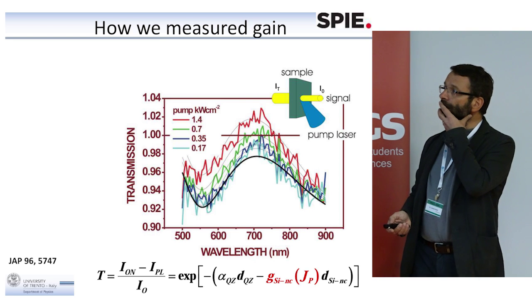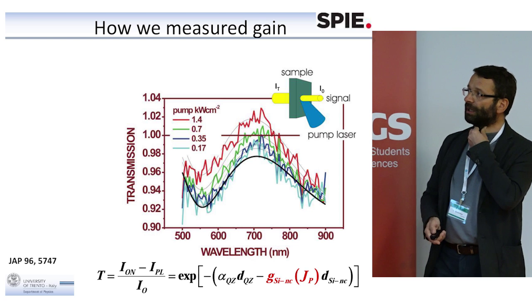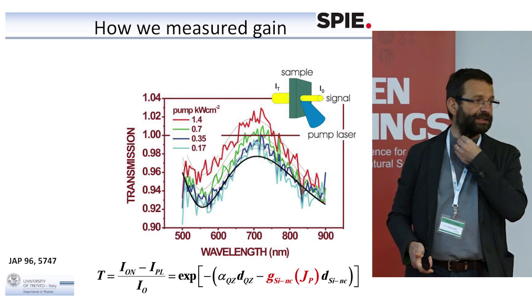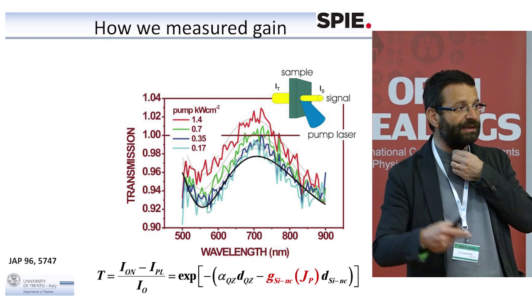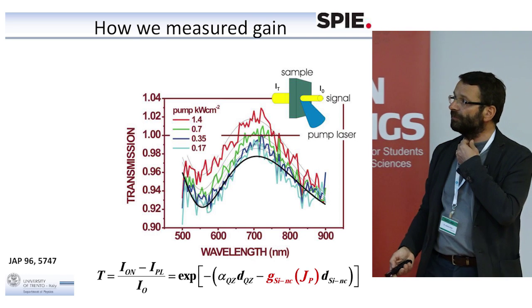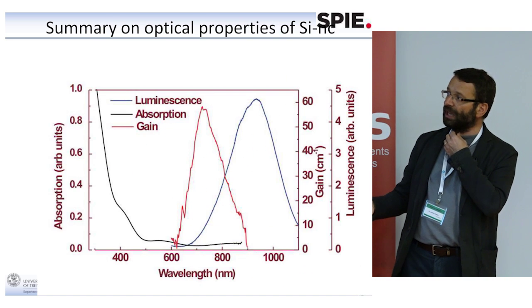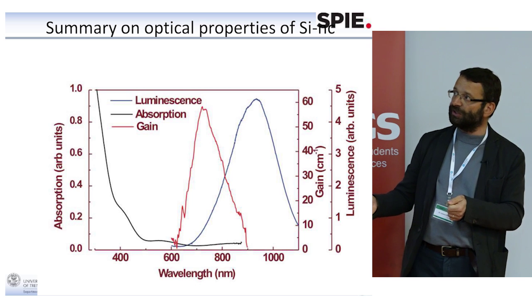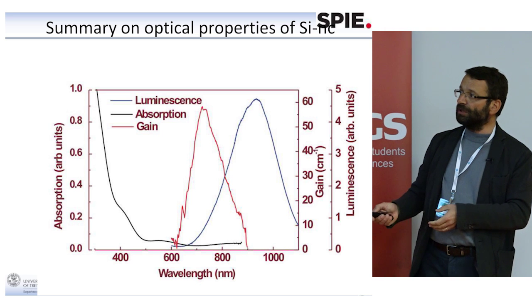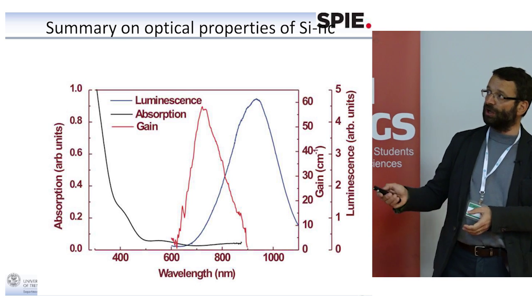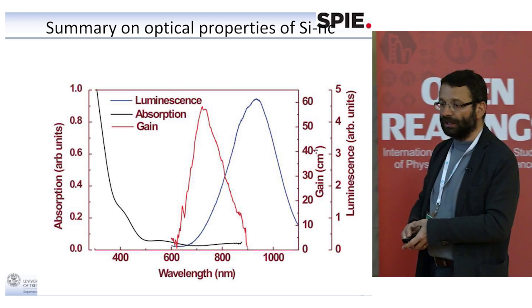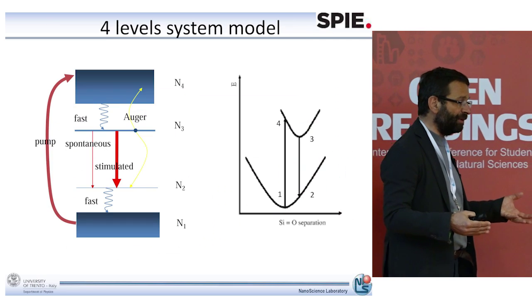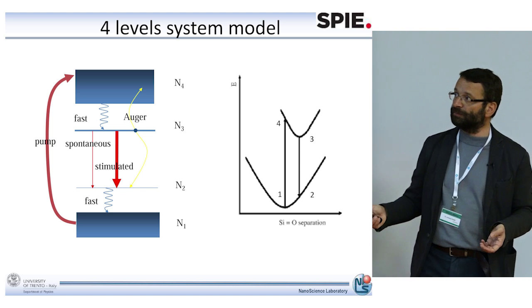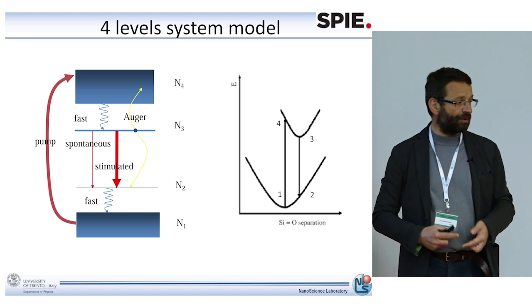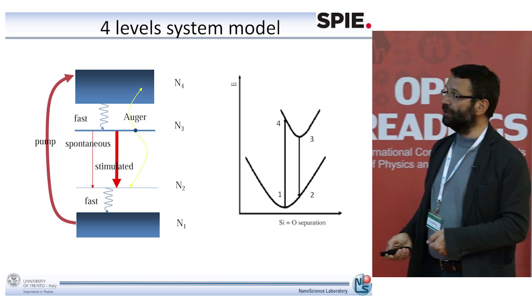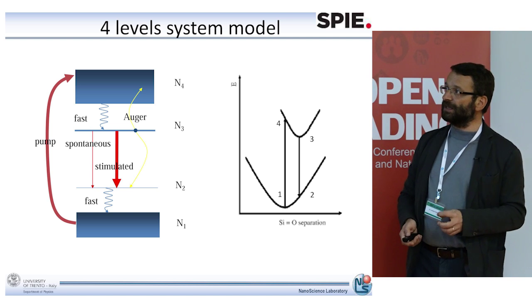So this is a result that is quite interesting in terms of the use of the nanocrystal to make a laser, because the first requirement for a laser is to have a material that is good to amplify light. Laser means light amplification, so you need to amplify the light. And so this is a good material for doing that. Here is an example that shows you that you have a gain peak at a certain wavelength region, and this is the black line that shows the absorption. And so if you look at the spectral dependence of the emission, the absorption, and of the gain, naturally you end up with a model for the gain that is a 4-level model. It's a 4-level model because you see that the absorption is spectrally separated from the gain. So that means that what you absorb is not what is giving you the gain. And so this is the model that we have developed in order to understand the physics of the gain in the nanocrystal.